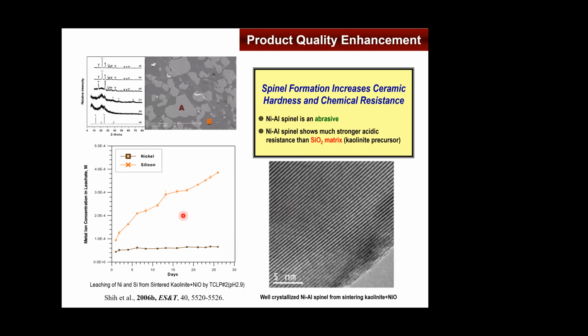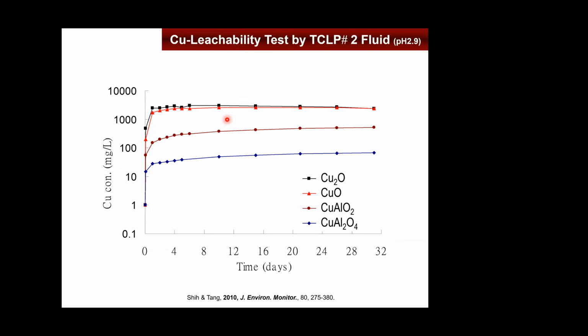So overall, you can see that it will be successful using the target mineral phase that you want to be very efficiently formed to stabilize your hazardous metal nicely, even compared to the silicon oxide. We understand silicon oxide, say in this case for the kaolinite sample, keeps being destroyed and keeps leaching out, but the spinel is still holding on to the nickel very, very tightly, maintaining very, very low leachable materials. So overall, we can see a similar trend by looking at different mineral phases, identifying them, and observing their leaching behavior. You will find a lot of new mineral phases like this one, stabilized by the alumina phase, will be much, much stronger compared to the oxide by itself, either the divalent or monovalent copper phase.